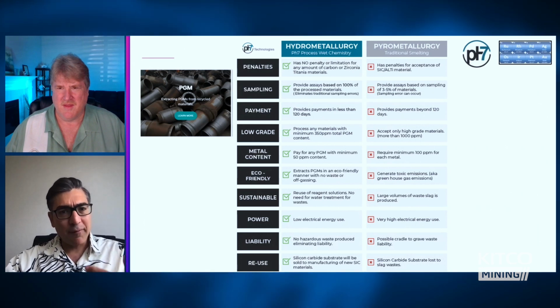Our whole process is actually faster. We get to about plus 50% purity of the PGM in less than a week after receiving the materials. It goes through the leaching process very fast and comes out of our electrowinning process at the end in less than a week. Then it goes to our refining partners, who refine it to separate it into 99.9% platinum, palladium, and rhodium. So it's a very fast process and a fast turnaround of the materials. Still, we have the bottleneck of the refining, because refining has to happen, but we are working with our partners to accelerate that as well.